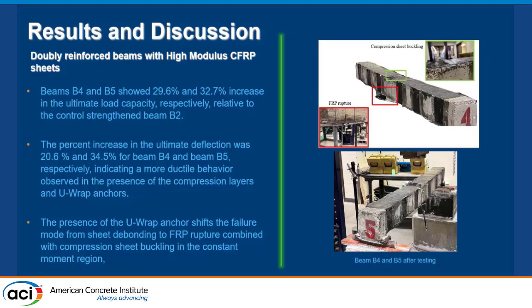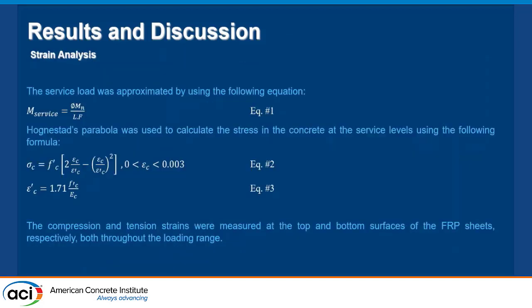So the U-wrap anchor shifted the failure mode from FRP debonding to FRP rupture combined with the compression sheet buckling in the constant moment region. We can see that the sheet buckles at the compression layer, and we have some FRP rupture material. So that's because of the added anchorage, which shifted the failure mode from debonding to this combined failure mode.